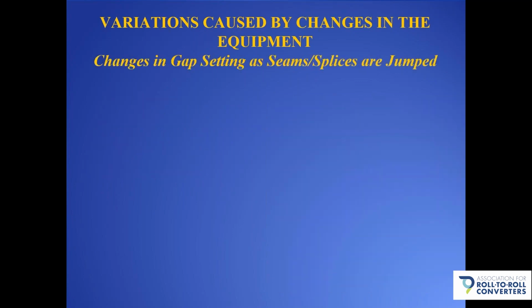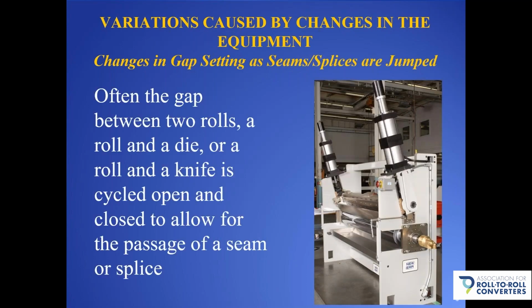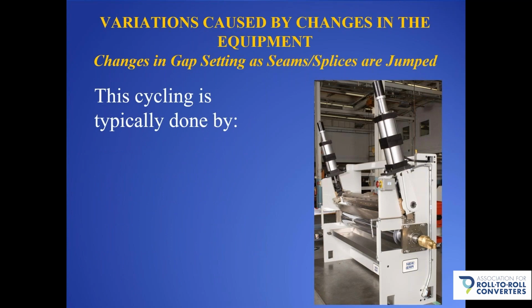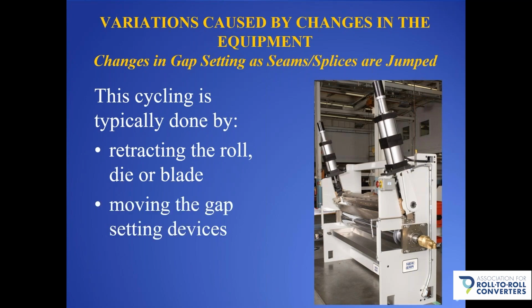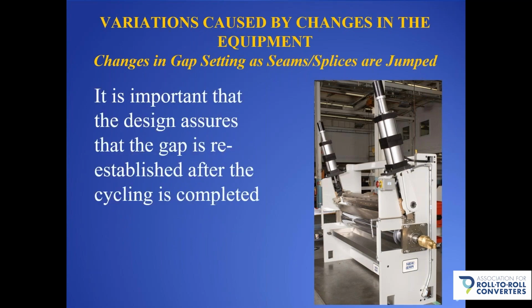Another issue is changes in gap setting as you jump a seam or a splice. Often the gap between two rolls, or a roll and a die or a roll and a knife, is cycled open and closed to allow for a seam or a splice to pass. And this cycling is typically done one of two ways, either by retracting the roll or die or blade, or by opening the gap setting device and then closing it again after the seam or splice passes. So what really becomes important is that the design assures that the gap is reestablished precisely after the cycling is completed. If it's not reestablished correctly, obviously you're going to have a change in your gap and therefore a change potentially in the coating laydown rate.